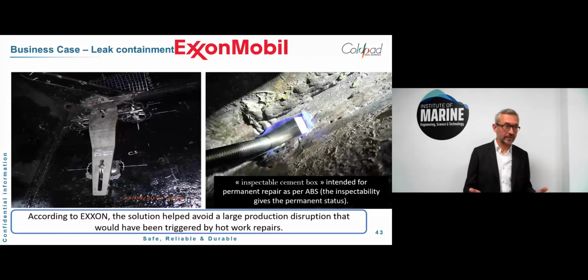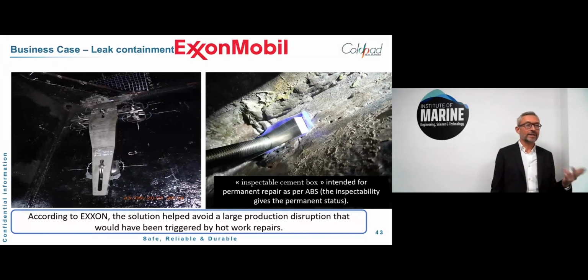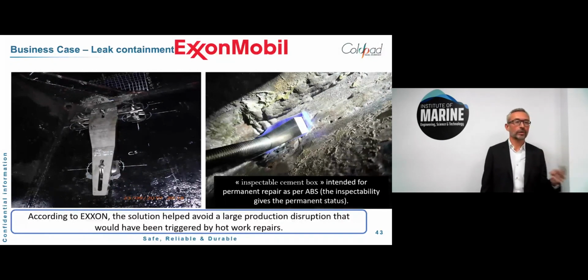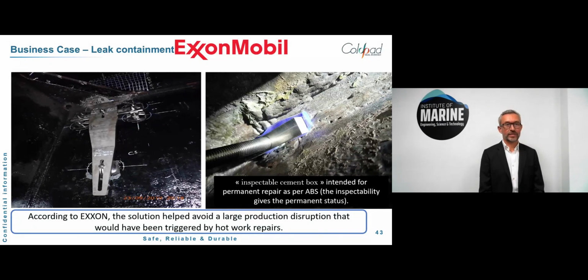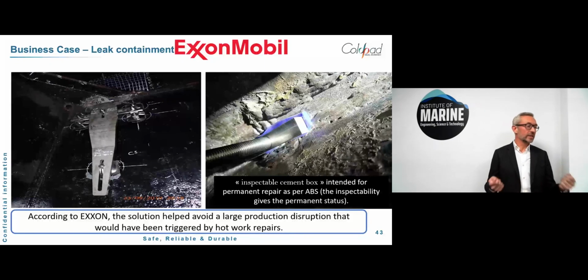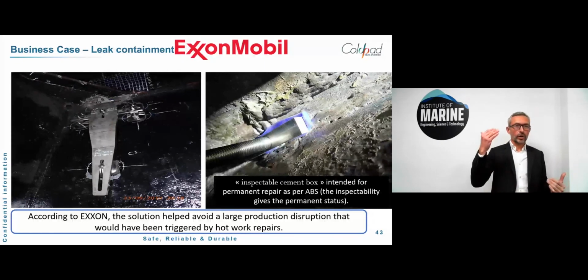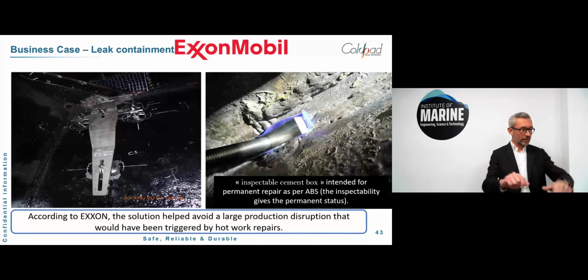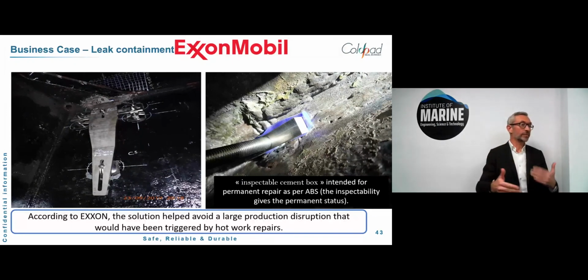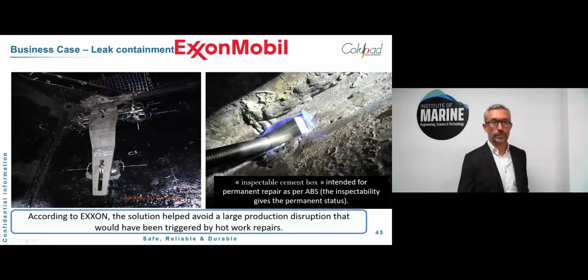So we did a mock-up for that in the lab, where we applied delta P with a gas, which was twice the actual pressure heads. It was working very well, and we applied that live, and it was inspected, and it works perfectly. The good thing is, even if permanent status is usually difficult to get, you can inspect, and if everything is fine, put it back, and then extend it for 5 years or whatever the inspection pace is up to the end of the life of your PSA.